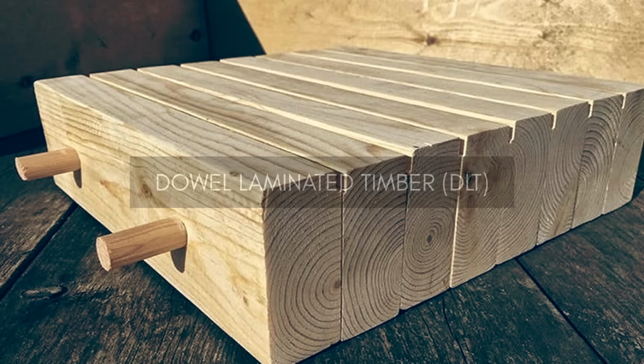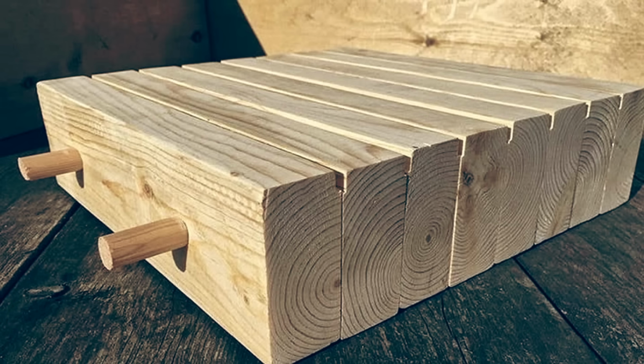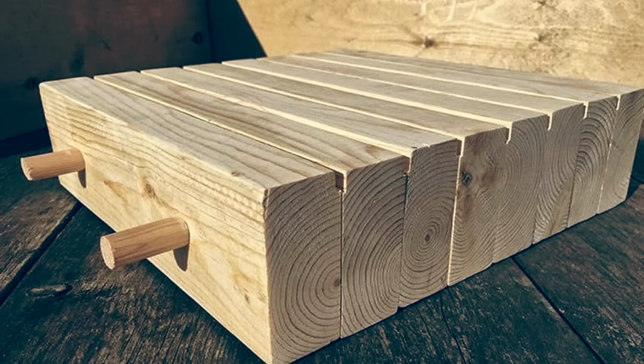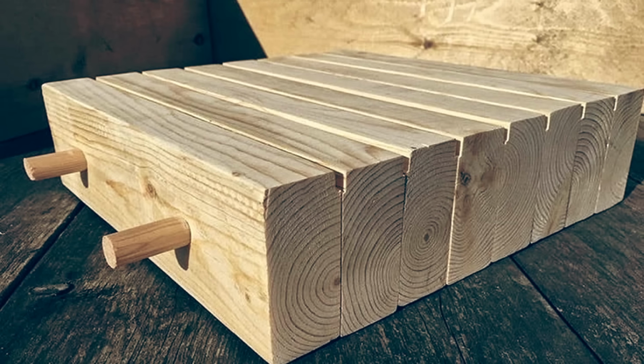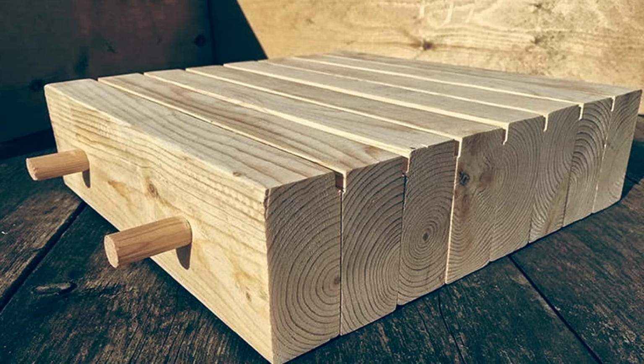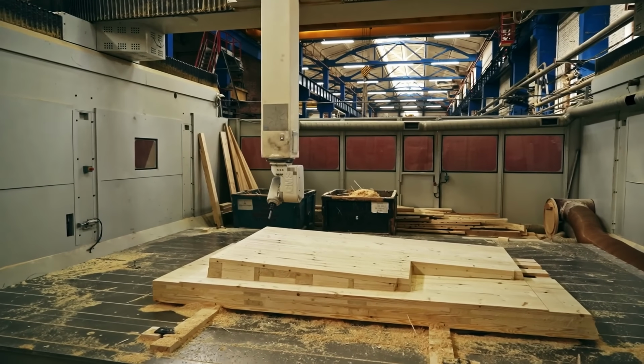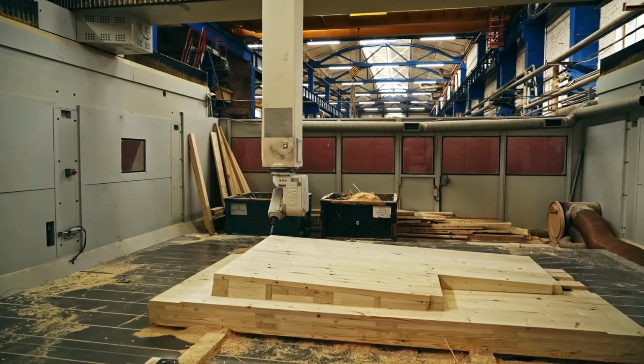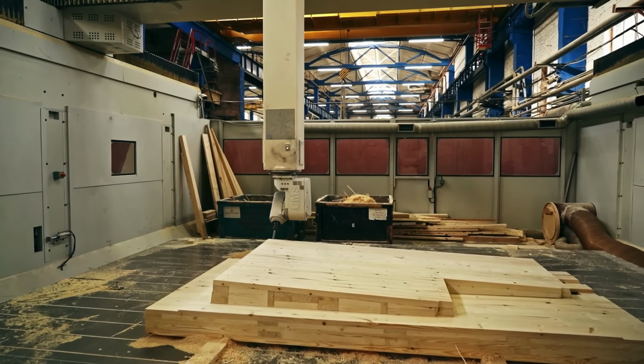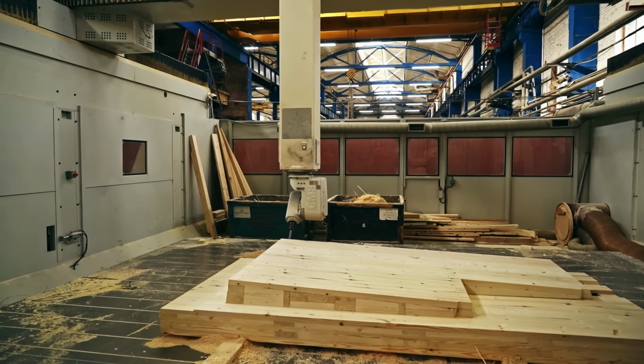Softwood boards are friction fit together using transverse hardwood dowels, dried to a lower moisture content than the surrounding lumber. Once inserted, the dowels absorb ambient moisture and swell, permanently locking the assembly. Because DLT is all wood, it is fully CNC machinable, enabling complex curves and acoustic profiling to be cut directly into structural panels.